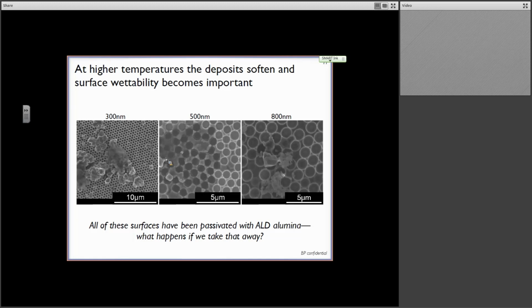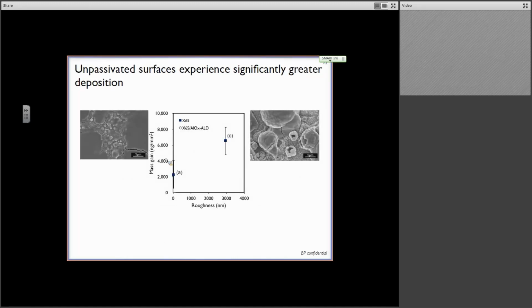Now I have to qualify a lot of this, especially these high temperature ones, with the fact that all of the surfaces I've shown you so far have intentionally been passivated with an atomic layer deposition layer of alumina, or aluminum oxide. We did this because we wanted to isolate the chemistry effects from the surface roughness effects. So the question is, what happens when we take that surface passivation, that layer of aluminum oxide, away? Well, this is what happens. What I'm showing you here in the center, and I'll show you quite a few of these plots, so it helps to walk through it, is the roughness of the surface, measured by surface profilometry, a consistent measure that we repeat for all of our specimens, versus the mass gain.